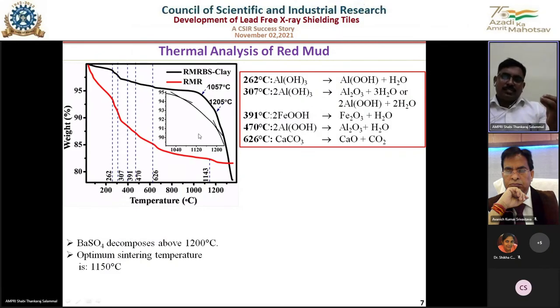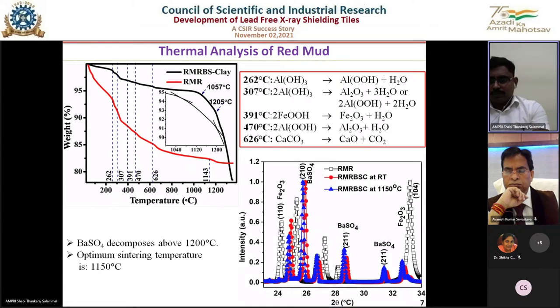And also here you can see at nearly 1200 degrees Celsius, there is a huge weight loss. Actually, this happens due to barium sulfate, and it is not good for such large scale production. So we fixed the temperature below 1200 degrees Celsius, and we found 1150 is the optimum temperature. So at 1150, you can see here, the barium sulfate does not decompose, and it is staying as it is, so it is suitable for making radiation shielding tiles through the sintering process.